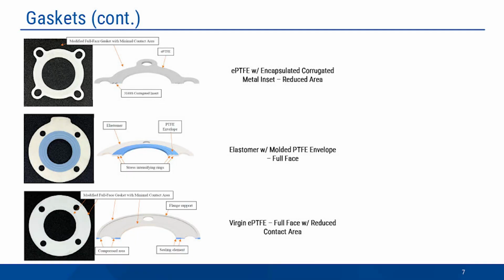And last is a virgin expanded PTFE. This is another reduced area design. This is separate from the other one where you are cutting out the areas that effectively aren't sealing or aren't supporting the flange. Here you have the ID as a raised face, which is doing all of your sealing. The area in between, technically when you compress it, you're not going to compress down to that, so that's not doing any sealing. And then on the OD, you have another raised face that protects the flange and also prevents the ingress of any foreign material into the flanges themselves.